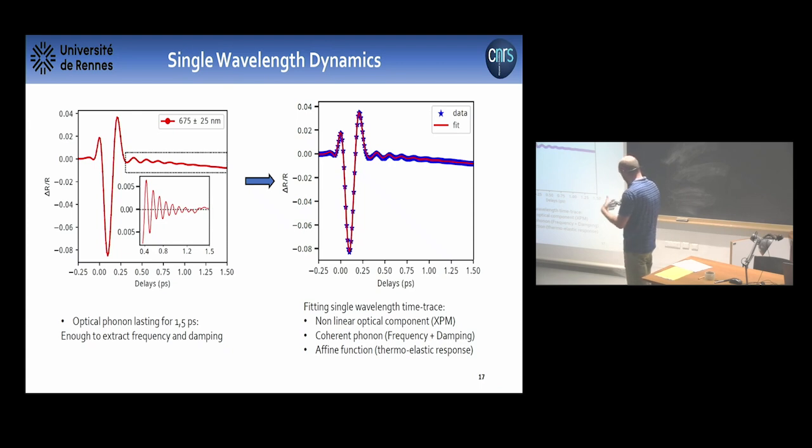So I hope you can trust me that we can easily extract frequency and damping with such data quality. And if you push further, you can even do the full fit of the time trace, meaning that you have the nonlinear optical component, the coherent phonon with frequency and damping, and some kind of additional affine function which is dealing with the thermoelastic response.